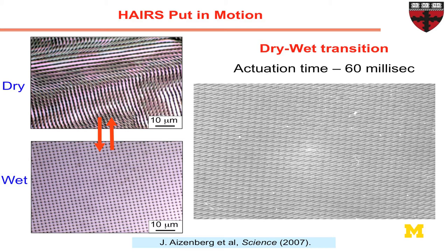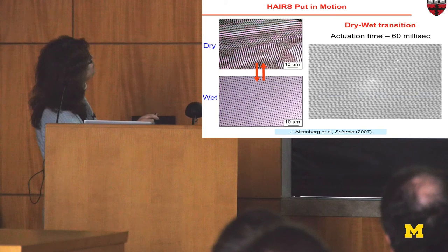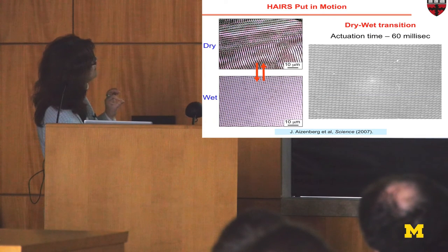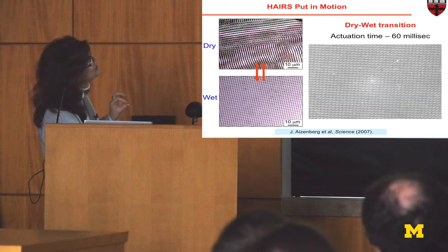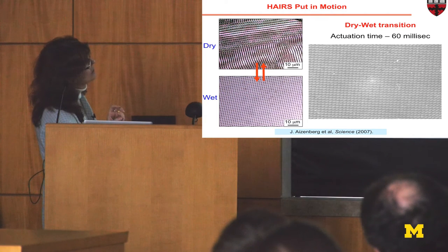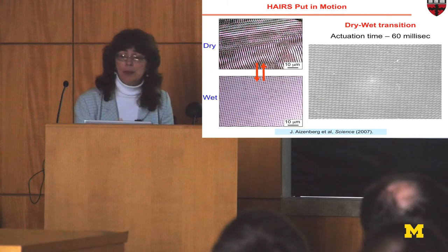So here is a simple take on dynamic materials that really was, in so many ways, affected by thinking about how plants open and close, and what is the simplest muscle we can imagine. But here's an example of these high aspect ratio structures put in motion. In the dry state, when the gel is contracted, they're lying down. Same region in a wet state, they're standing up. Here is the movie, and it's a very fast actuation. Here it is standing up, lying down, standing up, lying down.